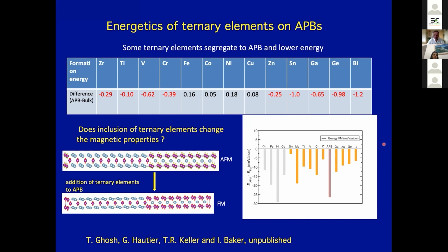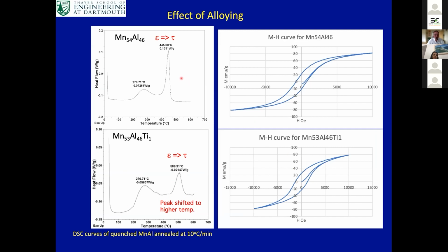And so what we did was we took one of these materials, and we're going to look at some others later, but we took one of these, titanium, and put it in manganese aluminum to see what happens. This is the graph that you saw earlier. This is when we put just 1% titanium replacing manganese in the material. And if you look at the two graphs, the low temperature peaks are essentially at the same temperature in the material, in fact, identically at the same temperature. This is the low temperature transformation, which we're not quite sure happens.